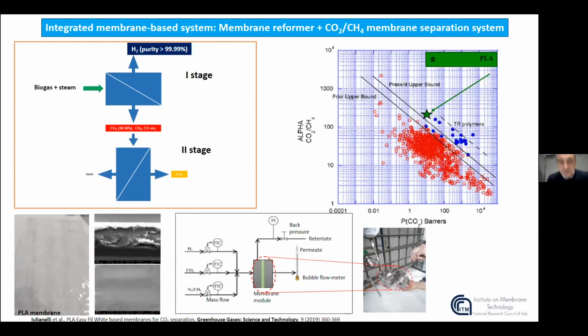Well, in this slide, I would like to show you an integrated membrane-based system to produce blue hydrogen, such as the membrane reformer as a first stage in which the biogas is fed, combined to steam to realize a steam reforming reaction to produce high-grade hydrogen permeation through a palladium-based membrane with the purity higher than 99.99%, and the non-permeated stream reaching CO2, eventual unconverted methane and carbon monoxide is then treated in a second stage process based on a